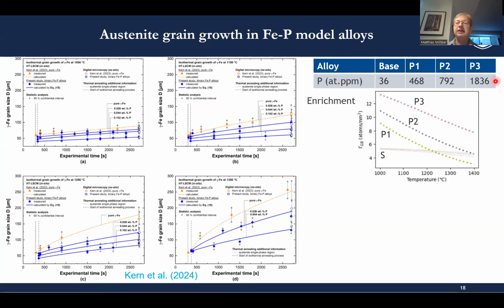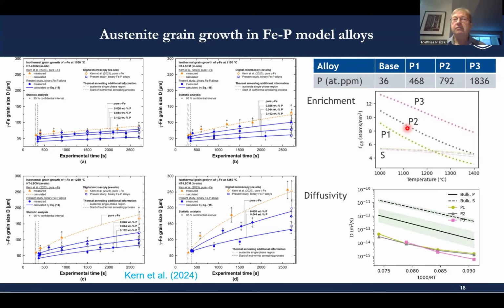And what we found is that sulfur is still segregating to this interstitial site, like in the electrolytic iron, but with increasing phosphorus content, phosphorus can occupy additional sites in the grain boundary, and this obviously increases with the phosphorus bulk content. And now we have to find out how phosphorus diffusion could affect the migration of the interface or the grain boundaries. We have to keep in mind that the diffusivity of phosphorus is actually lower than that of sulfur, and the slowest diffusing species is what determines this.